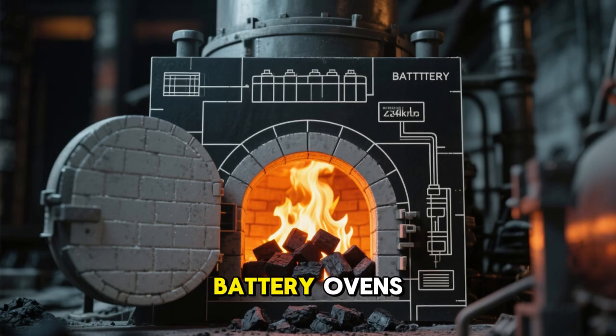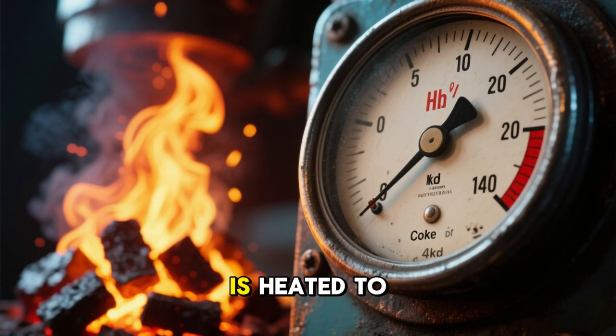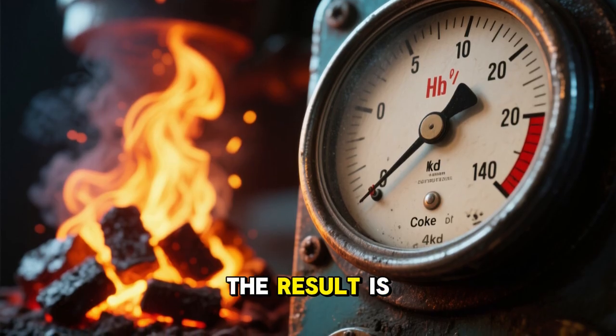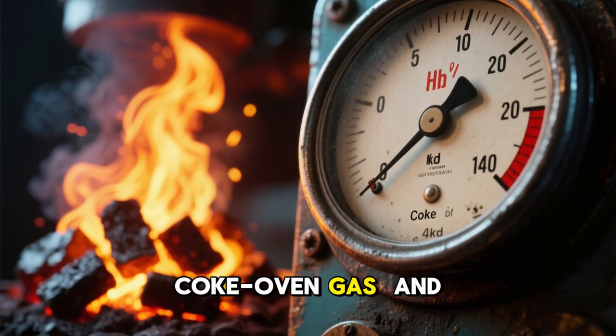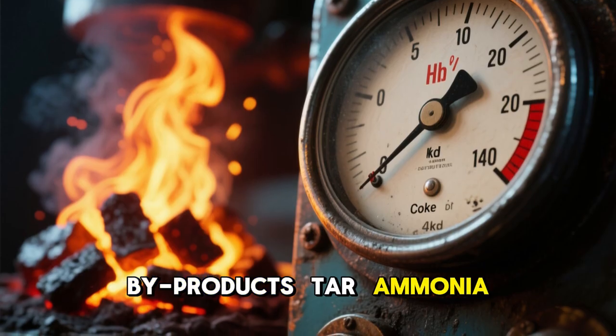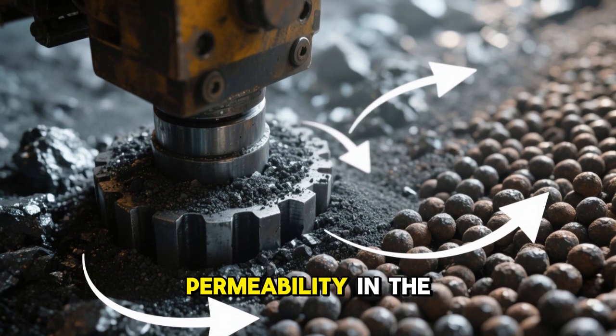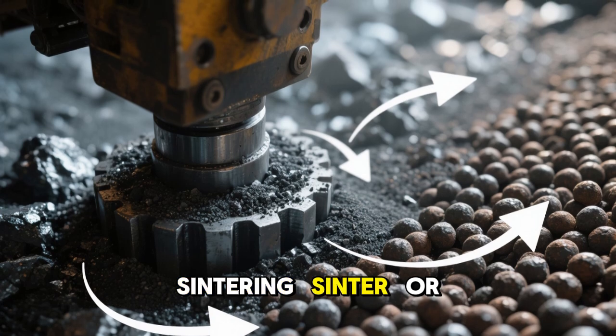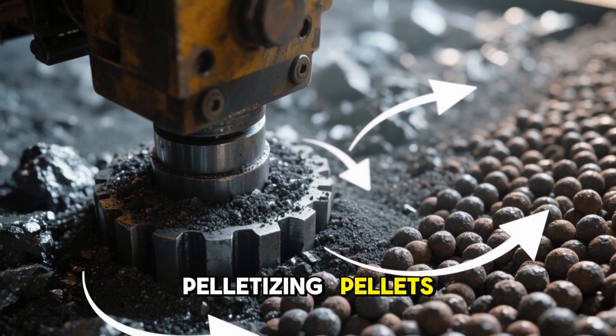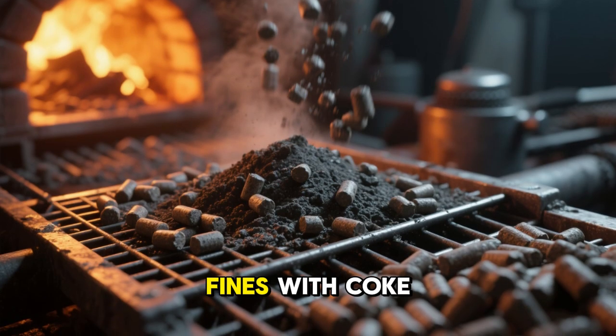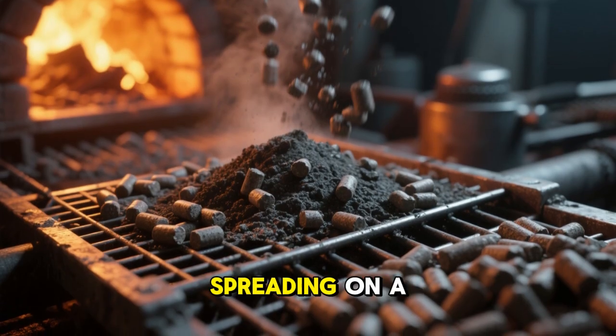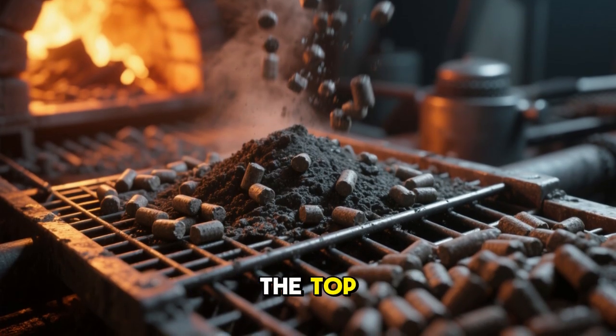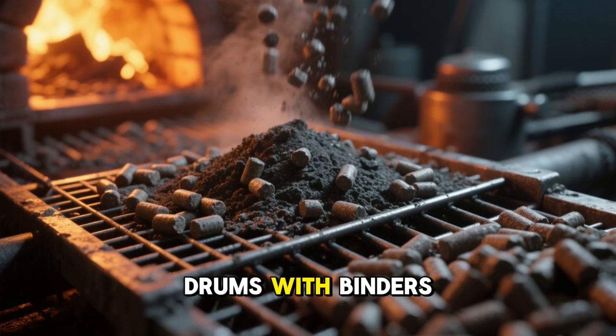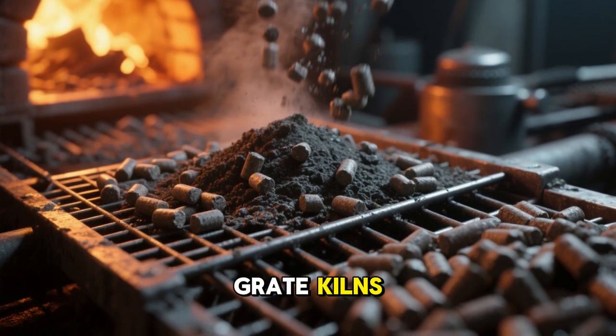In the integrated route, metallurgical coal is converted into coke in battery ovens. Coal, in the absence of air, is heated to about 1,100 degrees for 15-20 hours. The result is porous, strong coke, coke oven gas, and byproducts, tar, ammonia. Fine ore is agglomerated to improve permeability in the furnace: sintering, sinter, or pelletizing, pellets. Sinter is made by mixing ore fines with coke breeze and fluxes, spreading on a suction grate and igniting the top. Pellets are formed in discs or drums with binders, then indurated in grate kilns.